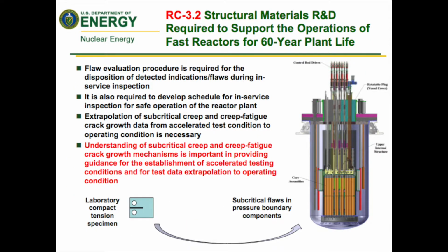The second topic, similar but different, also looks at how to extrapolate laboratory data out to 60-year lifetime, but this part of it looks at the flaw evaluation procedures and what is required to disposition the detected indications or flaws that turn up during in-service inspection. We also need to understand this relationship from laboratory to in-service conditions required to develop schedules for in-plant inspections. They're clearly going to be different than the LWR cousins that we are moving upward in temperature from. And we need to be able to extrapolate the subcritical creep and creep fatigue crack growth data from the accelerated conditions that are produced in the laboratory to what is going to happen over the extended lifetimes of these actual